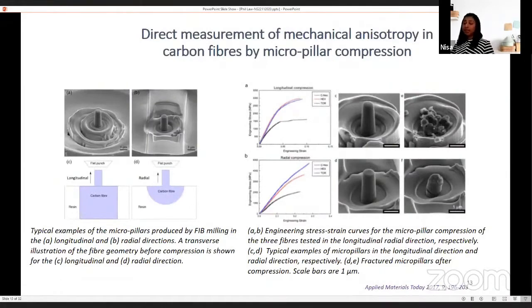It has been reported that carbon fiber anisotropy can cause premature delamination between fiber and the matrix, especially in some high stiffness composites. This happens mainly due to the fiber's unique microstructure and the graphitic carbon. Between the graphitic sheets, there are packets of amorphous carbon and voids. Although the tensile properties of carbon fibers are readily measured through robust and direct techniques, the determination of transverse properties of the carbon fibers is very complex because the diameter of the fibers is so small.